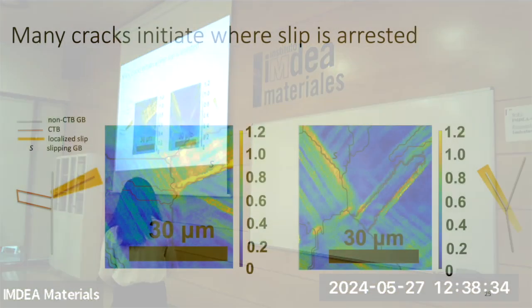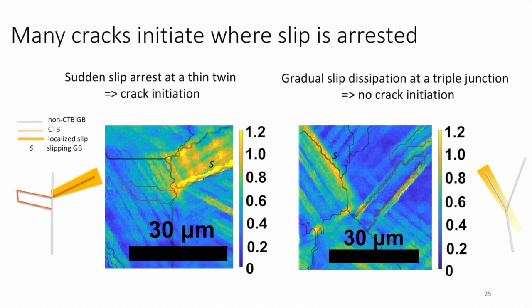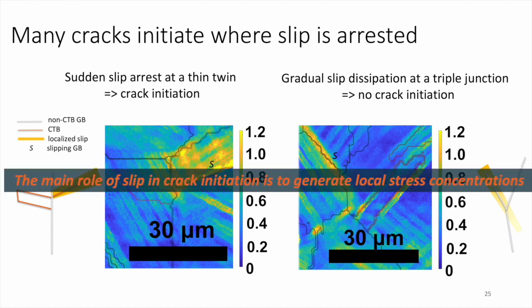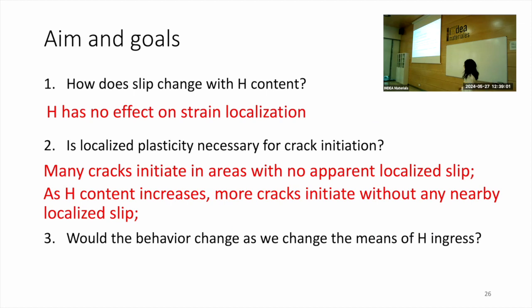In the second case, we do not observe any cracks. Here we have a triple junction, and the strain is concentrated going through this triple junction. What we see here is that the main role of the slip in crack initiation is to generate local stress concentration. So we answered the second question.